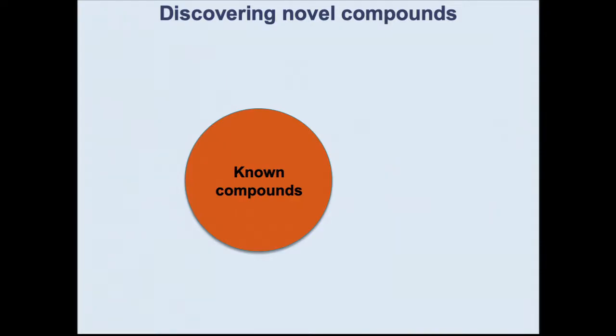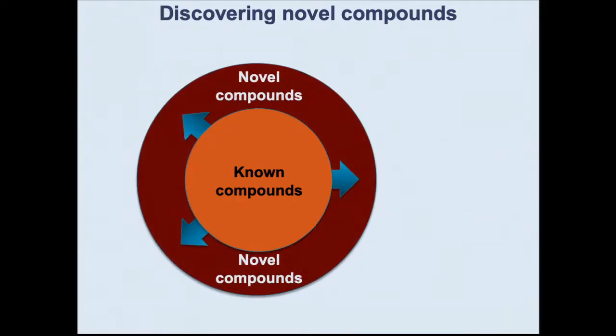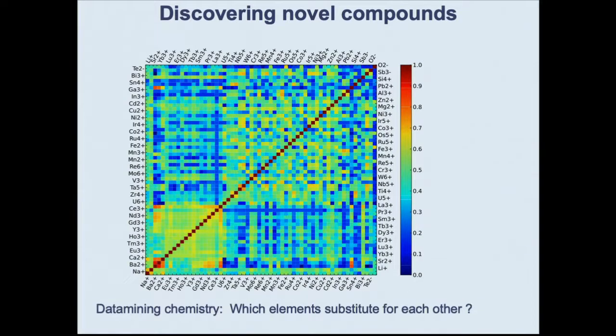But we also try to discover new compounds. And we do that with a fairly rigorous control technique. So we try to go from the known compound space to novel compounds. And the question is how do you make novel compounds? You just put randomly all elements together? And we essentially do that by data mining chemical knowledge. So what we do is we take the known compound set, which is on the order of 50 to 100,000, and we learn from that chemical substitution.